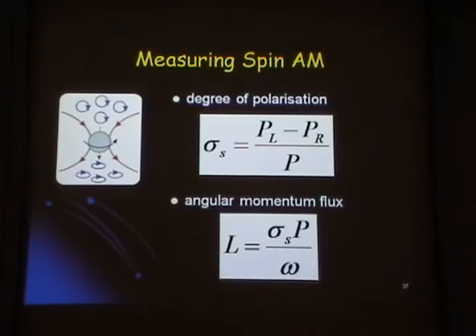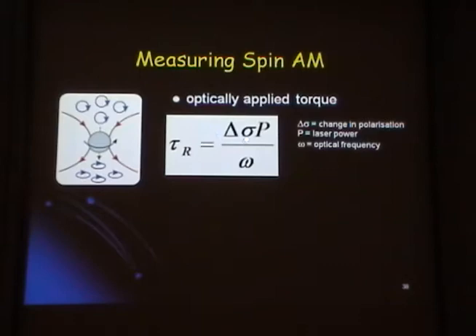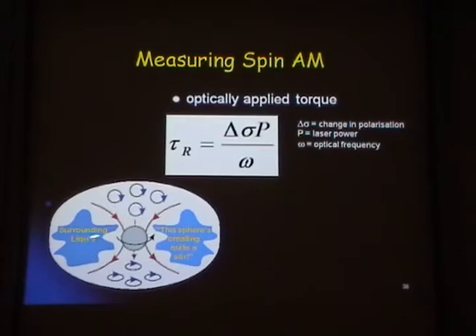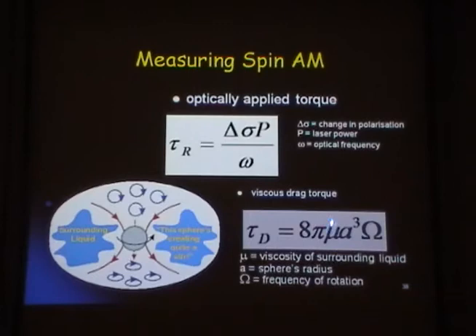Okay, now we also have angular momentum flux acting here, so I have this degree of polarization times power divided by omega, and then I also have the optically applied torque, which is the change in polarization times the power divided by the optical frequency. And of course, I have surrounding fluid, and so this will react to the rotation of the particle. So I have a viscous drag torque, which goes like 8 pi times viscosity times the sphere's radius to the third times the frequency of rotation. Okay, and these two should balance now,